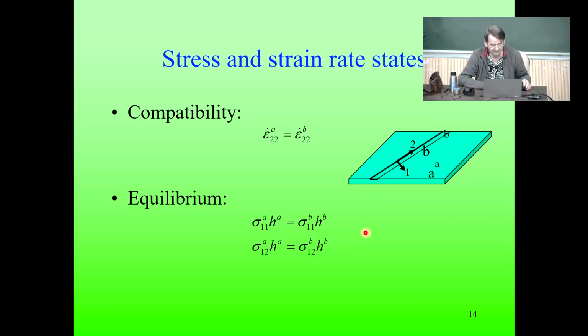The other is the equilibrium equation, so that the forces are transmitted across between the left and right part of the groove. From left to right, the forces are transmitted through the groove. So when you calculate the force, for example, in direction 1 in the groove, this is the stress component multiplied with the thickness, it has to be the same in the matrix zone. And also the shear component is transmitting the shear stress. If there is shear stress, and of course there is, because forces are working in different directions, there is sigma 1 2.